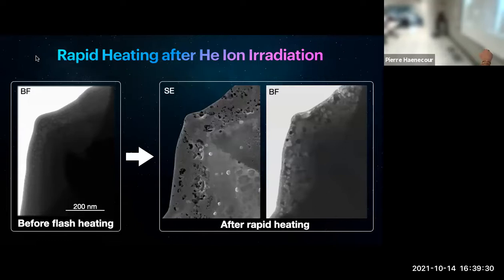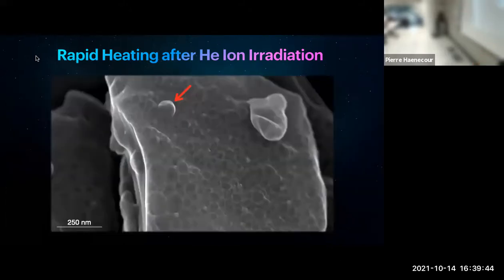If you look in the transmission bright field image, you can see that in addition to changing the structure inside the sample, so you don't have the helium trapped inside anymore, you actually form iron nickel nanoparticles all around. Here on the surface, you can see again this texture, showing you the release of all the helium, those open vesicles that released all the helium that was trapped. And then even the formation of those iron nickel nanoparticles on the surface of the sample. So it's actually a 3D particle that forms on the surface of what used to be an olivine grain.